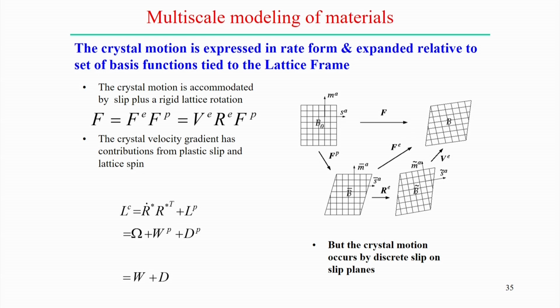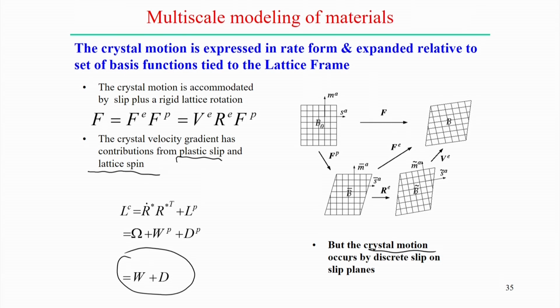So crystal motion is expressed in rate form, and the expansion is related to a set of basis functions tied to the lattice frame. In a different frame, the crystal motion is accommodated by slip plus a rigid lattice rotation. So the crystal velocity gradient has contributions from both plastic slip and lattice spin. These two components explain the motion in terms of rate form. This is the reason we sometimes represent the hardening law in crystal plasticity as rate dependent, since crystal motion occurs by discrete slip on the slip plane.